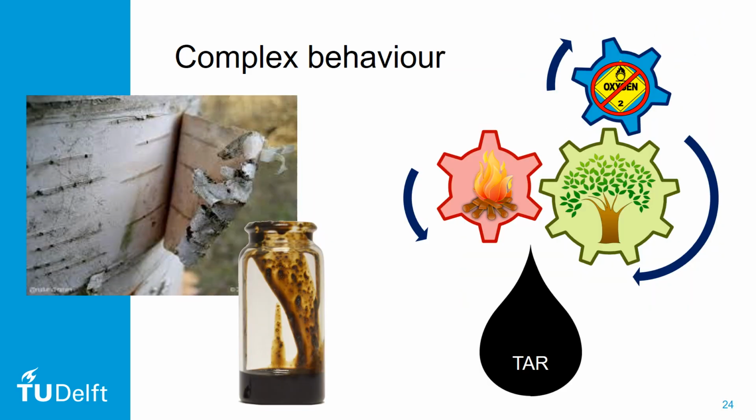Now tar gives us insight into the technological capabilities of Neanderthals. And as I just said, my interest is in technology and its complexity. Now first, tar making is a bit like kitchen chemistry. It is impossible to predict that when you have bark, tar is going to be the end product. The materials are very different. And to make tar, you need to heat the bark between 300 and 600 degrees, and you have to make sure no oxygen gets into the reaction chamber. This way, the tar does not burn. Next, you catch the tar dripping from the bark.